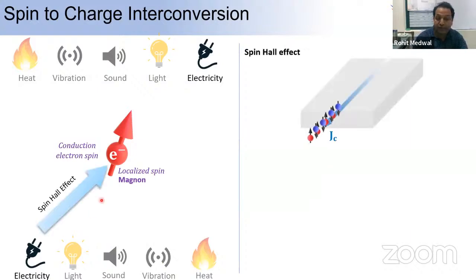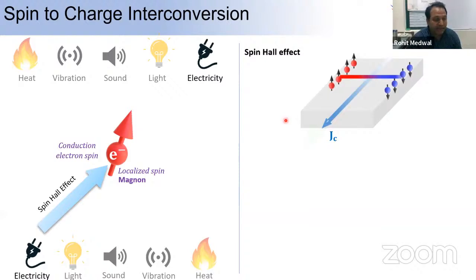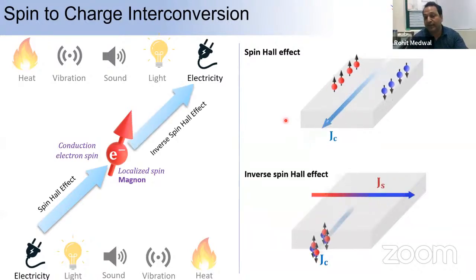We are mainly working on the first, where we use electricity to convert the charge current to a spin current, which we call the spin Hall effect. We apply the charge current through a conductor which has a high spin orbit coupling, or spin Hall material. Because of this spin orbit coupling, the unpolarized charge current passing through gets spin polarized. As a result, you will start accumulating the spin polarized current at the interfaces. This is called the spin Hall effect. And we can convert this spin, which is being generated, back into the charge current using the inverse spin Hall effect, which is the vice versa of the spin Hall effect.